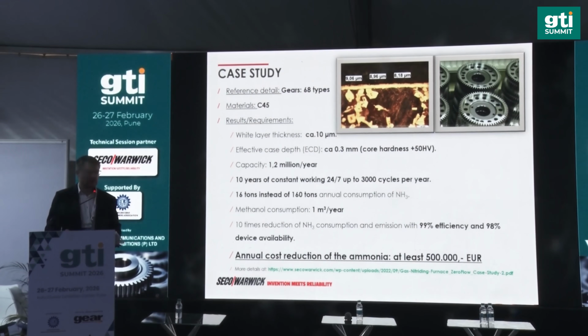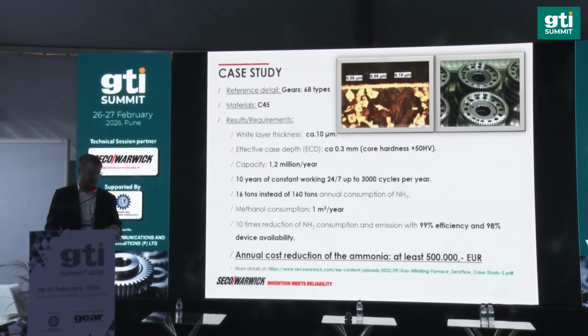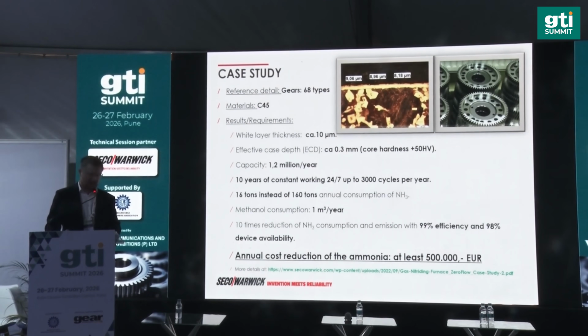We are talking about 1.2 million gears per year, and that was the first challenge for us. The second challenge was the ammonia consumption and emission of gases, because the company was placed in the middle of the town, and they used to use a traditional pusher solution. Our installation brings a reduction of the consumption by 10 times. They used to use 160 tons of ammonia per year, and thanks to our application, the consumption was reduced to 16 tons per year, and the whole installation is making around 3,000 cycles of FNC processes per year.